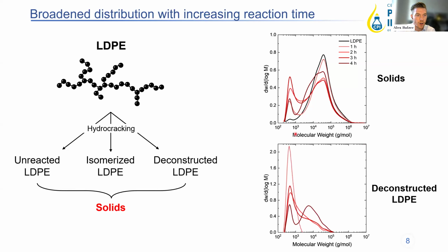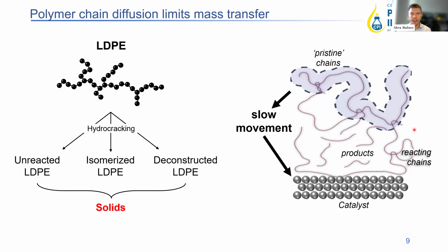And what we see is that early on in the reaction, after 1 hour, we get a large amount of deconstructed LDPE at very low molecular weights. But then as the reaction progresses, this distribution starts to widen and you get a lot more intermediate molecular weights. And what that tells us is that there is a changing mass transfer and diffusion aspect during the reaction. We can think of it in terms of how fast polymers actually diffuse and how fast their diffusion viscosity is compared to general materials you may see in everyday life.